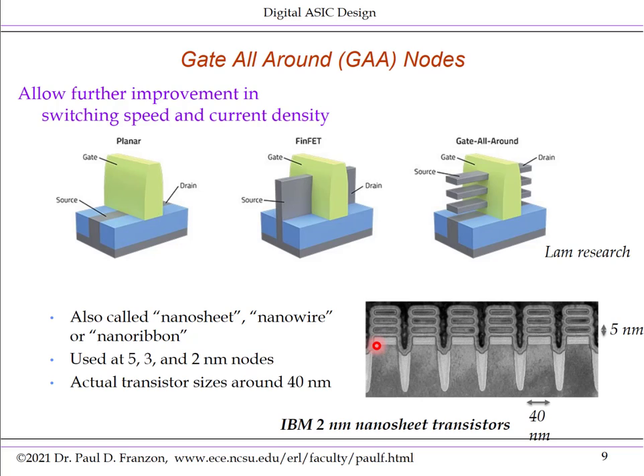Here's a cross-section from an IBM publication about their 2nm node, which they've just introduced in R&D. What you see here are three nanosheets or gate all-around structures. The width of the transistor is 40nm — these are not 2nm-sized transistors. Each gate, including the channel and oxide, has a vertical dimension of about 5nm. This illustrates that there are nanometer-sized features in the gate oxides, but the transistor footprint and metal footprint are pretty much back to what they were at the 22nm node.